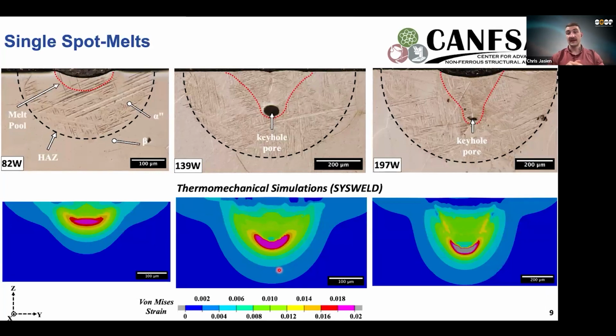And so overlaying the simulations on top of the exact experiments, we see a very good correlation, where essentially what's happening is as we increase the power, moving from left to right of these samples, we see an increase in the amount of not only this alpha double prime phase, or this martensite phase, in the melt pool, but also in this heat affected zone region. And we see that in the simulations, where as we increase our power, we see not only an increase in the amount of area affected by strain, but also a larger magnitude of these strains. So this just confirms that this is a strain driven process, and that the increase in the amount of this strain induced transformation is a cause of the increased strains from the increase in power.